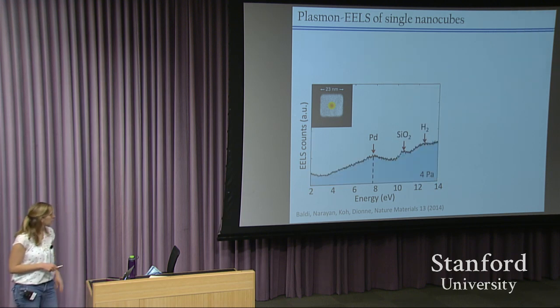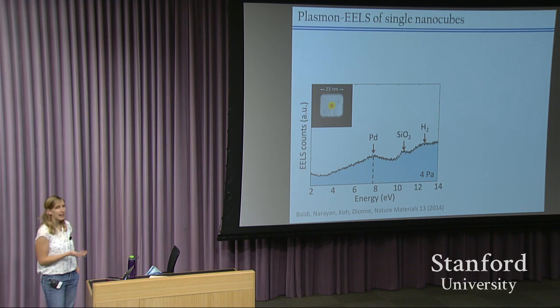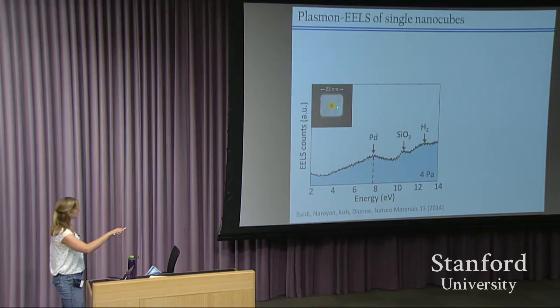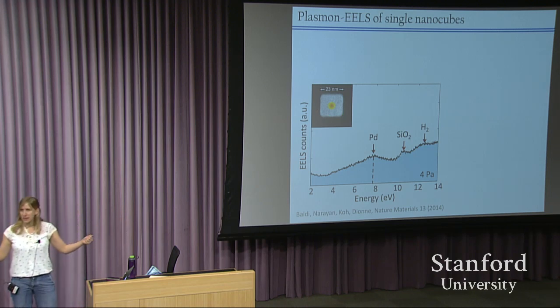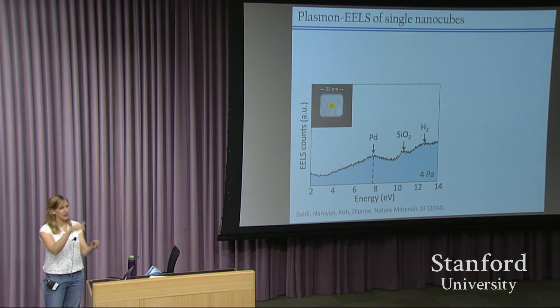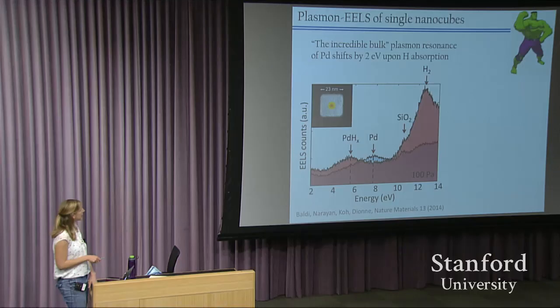For those of you who have taken, say, an optics class or an electronic materials class, you probably know that bulk plasmon resonances are spherically symmetric breathing modes of electrons in the nanoparticle. You can almost think about this electron beam as being a point negative charge, so all of the conduction electrons in the palladium are going to pile up at the edges because they're repelled from the electron beam, and then when the electron beam has passed through, all those electrons relax back into the center of the nanoparticle. So they're kind of breathing in and out. That's that peak that occurs here at about 8 electron volts.